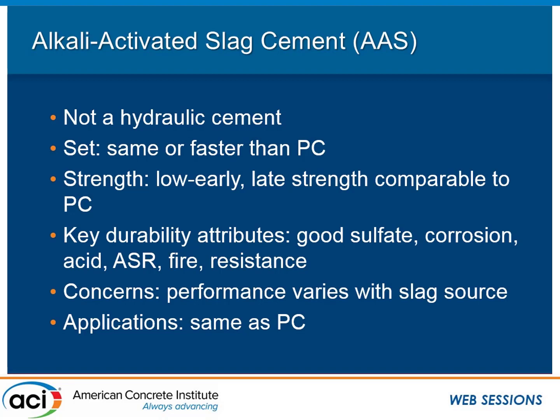So for those unfamiliar with alkali-activated cements, I should have said, essentially you take a material rich in silica and alumina, amorphous ideally, and react it with a high pH activator: sodium hydroxide, potassium hydroxide, sodium silicate. And it sort of just pulls it apart and polymerizes it back together, kind of like Jello. And you can do this with a very wide variety of materials. Essentially anything you would want to, you can use natural pozzolans, pretty much any pozzolan that's out there, but you will get, like I said, different properties.